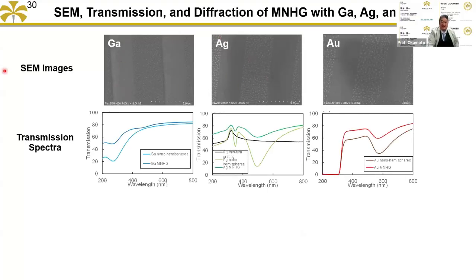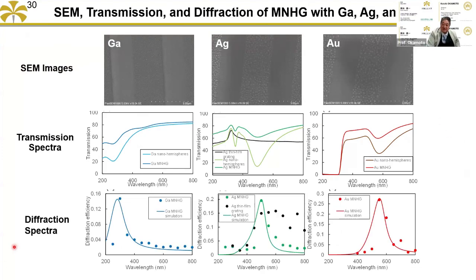And then that's the resonance peak in the transmission spectra. And that's why, for the whole structure, it's a grating structure. For the grating structure, the metal particle area becomes half. That's why the resonance peak becomes half. But in the gallium case, it's a deep UV light region, and in the silver case, that's a green light region, and in the gold case, that's a red light region. For each wavelength, we can obtain the resonance peak, and that's why it is a diffraction spectra.